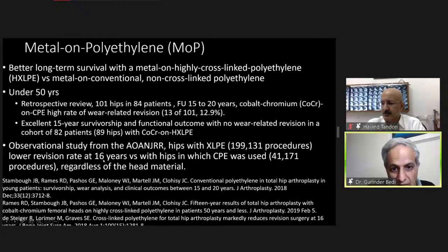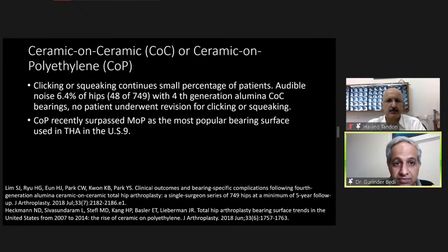So this is the Australian and the New Zealand registry. If you're using XLPE, now that's a huge number. So about 2 lakh procedures, lower revision rate at 16 years versus if you use a conventional polyethylene procedure. So huge numbers, and again, the evidence is very, very clear.